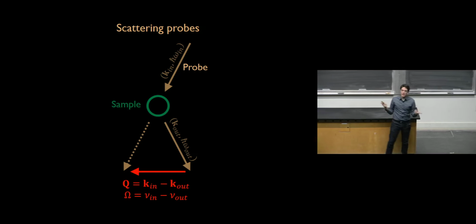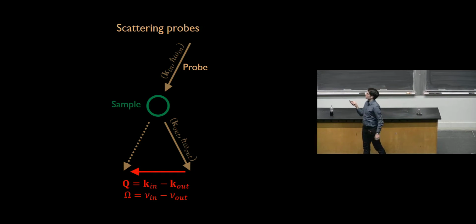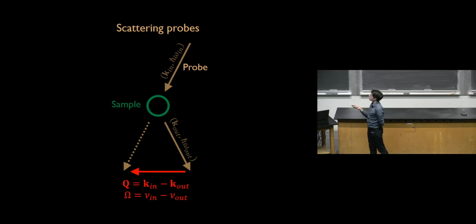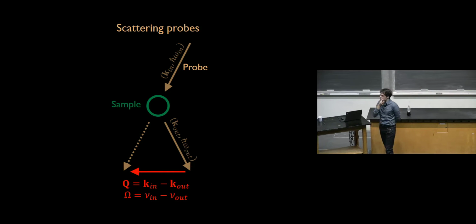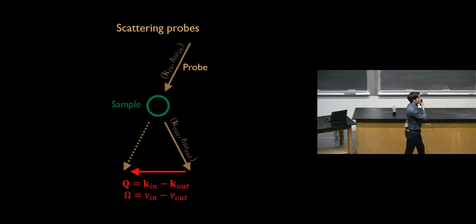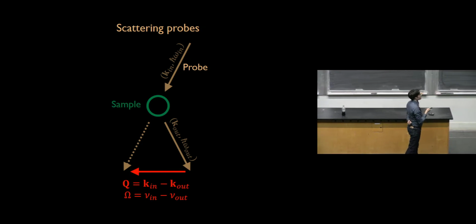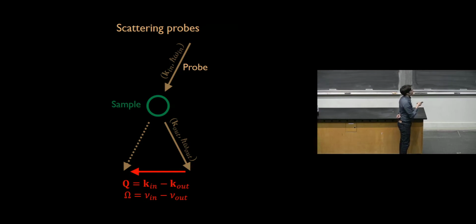So if the probe doesn't interact with the sample, then its momentum will not be affected by the interaction process. So these two values will be the same, and the total transfer momentum will be 0. And if the probe interacts with the sample, then in principle we can exchange momentum with it. And to exchange different momenta, or to look at some property as a function of momentum, the only thing you need to do is collect the scattered probe, the scattered particle, as a function of the angle. By changing this angle, you will change the wave vector of the outgoing probe, and that allows you to change this Q, because typically this is fixed.